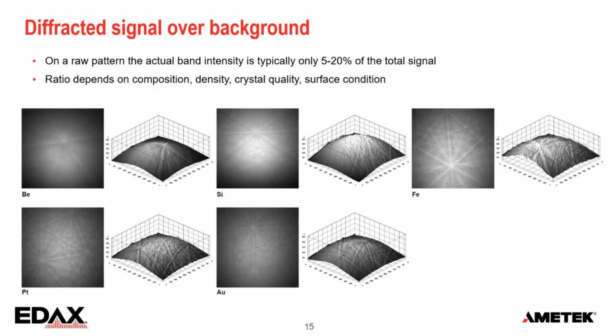And here are similar plots for a sequence of materials going from very light materials, beryllium. And here the bands are almost painted on the intensity gradient. There's almost no contrast in there. So that's probably less than 5% of the electrons that are actually giving us the bands. And if we go to heavier materials, silicon, iron, you start to see the bands really standing proud of this intensity gradient. And then it's very easy to find those bands. But still only around 15 to 20% of the total signal. So 80 to 95% of whatever we get is not what we want. And of course, that also happens when we are going to look at beam sensitive materials. We are still going to have to throw away 90% of the signal because it doesn't contain the information that we need.